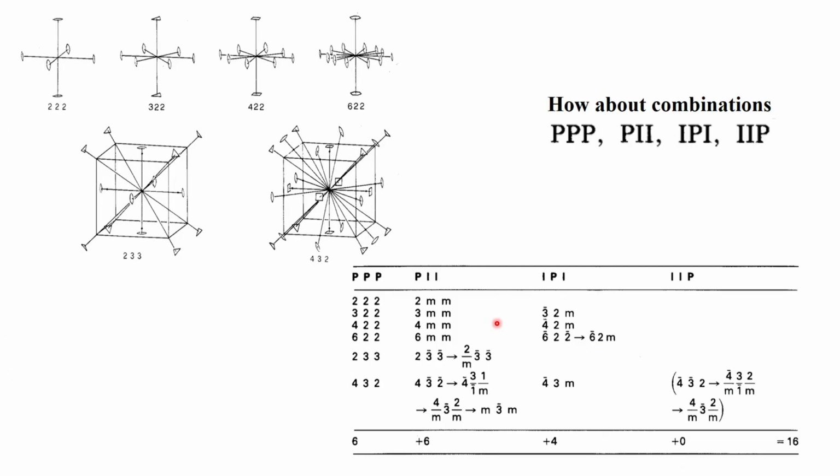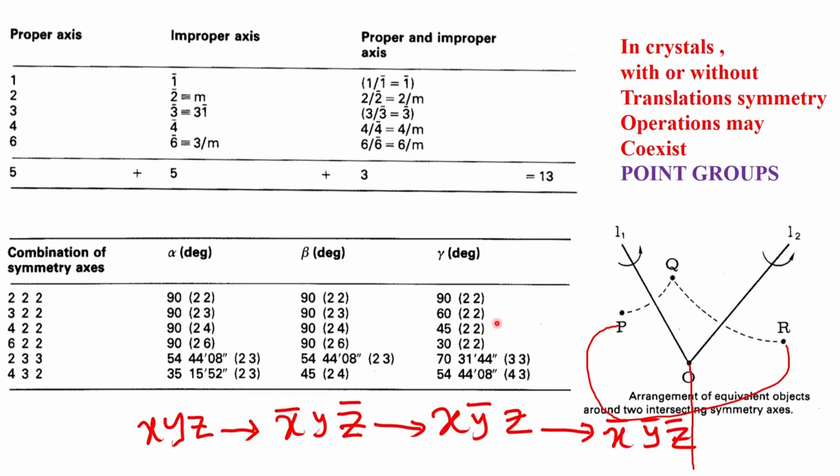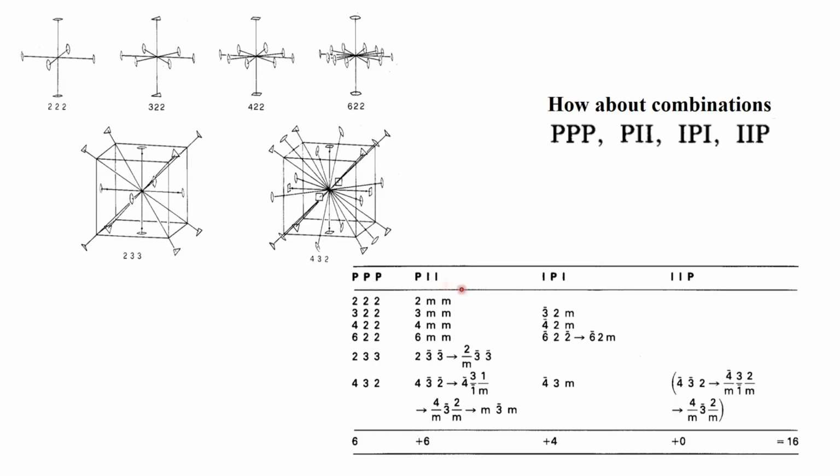In fact, this slide is almost immediately relevant. We have illustrated here the 2-2-2, how the 3 90-degree angles come with respect to each other. If you look at 2-2-2 here, the angles are 90 degrees with respect to each other. The next slide shows the 2-2-2 orientation. You see that the 3 are oriented at 90 degrees to each other. You see the relevance of the presence of the 3-fold axis in terms of the 60-degree angles, because you now get 1, 2, 3, 4, 5, 6, a hexagonal arrangement of the points on which the point group operation occurs.